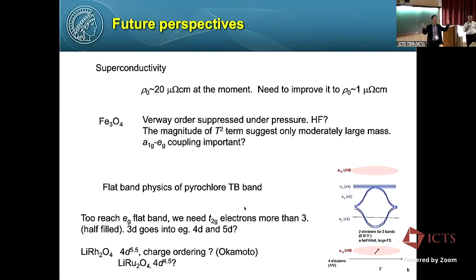So at the moment, my evidence comes only from the strain-induced static order set. Of course, above that, we should be able to see some signature of charge frustration. And perhaps we should do X-ray inelastic scattering to see the charge correlation. We have a bunch of crystals, so we should be able to do so. But at the moment, we don't have any data. In the spin case, there are a number of inelastic neutron scattering data, and they do see quite complicated spin fluctuation.